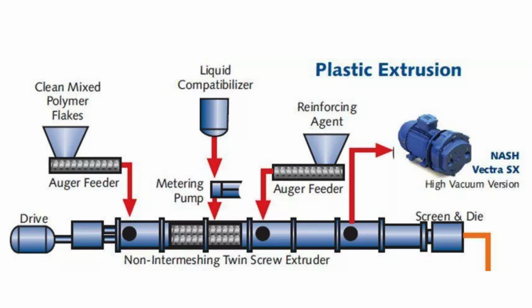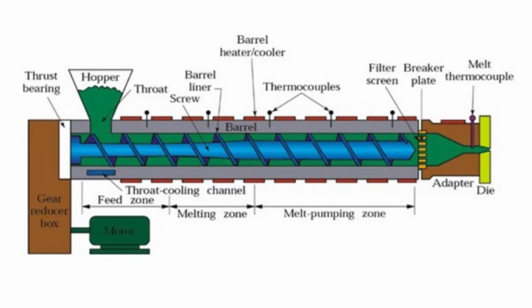The apparent viscosity at a constant shear rate as a function of the number of extrusions decreases gradually as extrusions are repeated because of the degradation of the matrix polymer and a reduction of the fiber length. An increase in the number of extrusion cycles decreases the length of the fibers. During the first extrusion, severe damage to the fibers was already observed regardless of the extrusion speed and shear rate used. Extrusion is an energy-intensive process.